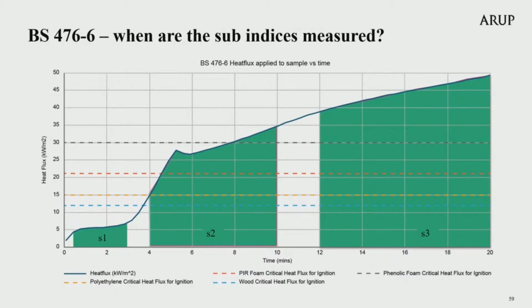I have now added to this comparison graph the time period when the temperatures forming the index S1 are actually calculated. During this period, please note the heat exposure to the specimen is actually less than that required to ignite wood or polyethylene. I have also marked the time periods when the temperatures forming the sub-index S2 and S3, little s2 and little s3, are also calculated.